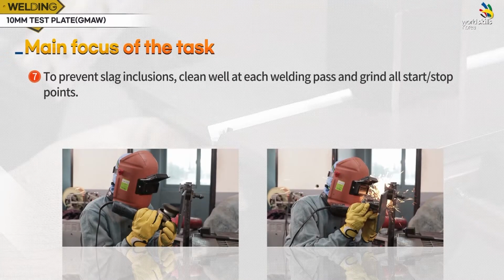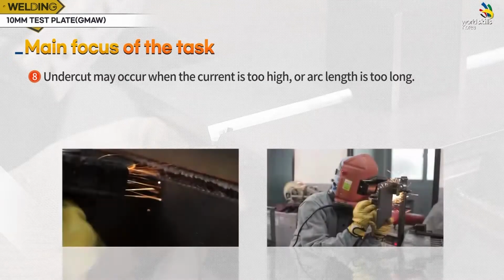To prevent slag inclusions, clean well at each welding pass and grind all start-stop points. Undercut may occur when the current is too high or the arc length is too long.